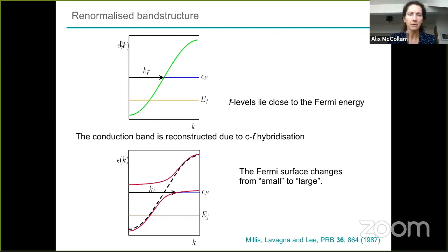So here I plot the energy versus momentum, and this would just be a conduction band, a relatively parabolic conduction band. This is the Fermi energy, and this would be the localized F electron levels. As I said, they're very close spatially, sitting towards the nucleus or the atomic core, but energetically they're almost degenerate with the conduction electrons. So they sit rather close to the Fermi energy. And this would be the size of the Fermi wave vector.